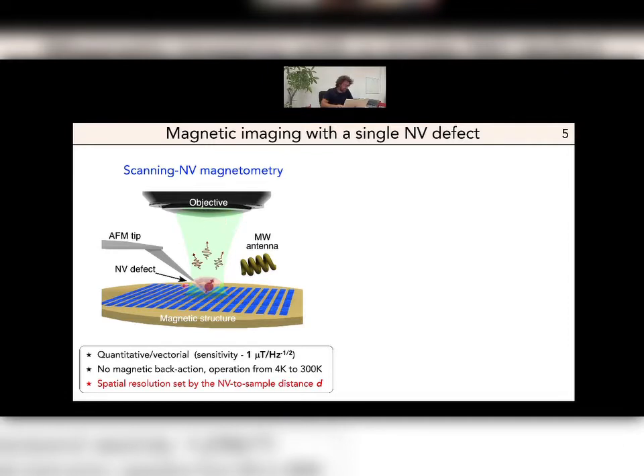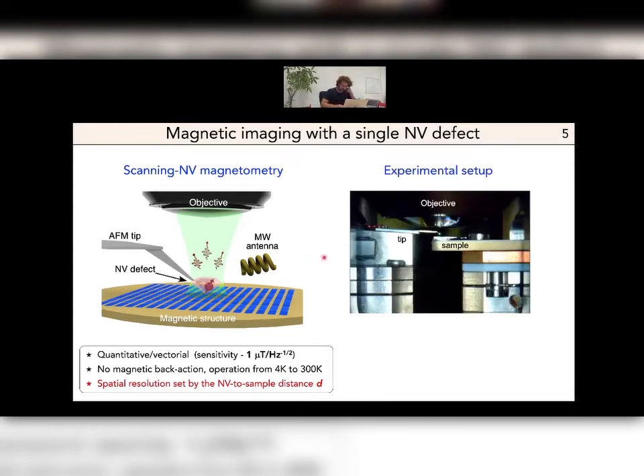So this instrument has some key properties. First, the measurement is quantitative, with a sensitivity that can go even below the microtesla for 1 second of acquisition. It's also vectorial because we probe a given projection of the magnetic field. But what is very important, I think, is that compared, for example, to magnetic force microscopy, here there is no magnetic back action. So we can consider, to first order, that the sensor in itself is not modifying the sample that you are looking at. Regarding spatial resolution, I told you that the field is probed within a detection volume that is given by the size of the NV defect, that is 7 nanometers. But in fact, the resolving power is set by the distance between the NV defect and the sample. So this probe-to-sample distance is really the important parameter in all experiments that will actually fix the resolving power of the instrument.